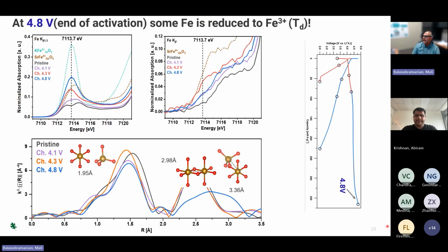Now, if you go to 4.8 volts on the other hand, what you find is that the intensity actually falls down in the K beta 1,3, but the intensity increases in the K beta prime. It is well known that if you have iron in a tetrahedral site, you should expect a significant intensity here because of the absence of a center of inversion symmetry in a tetrahedral site. So we believe that what is happening here is that the iron is getting reduced when you go to 4.8 volts, and some of the iron moves into a tetrahedral site.